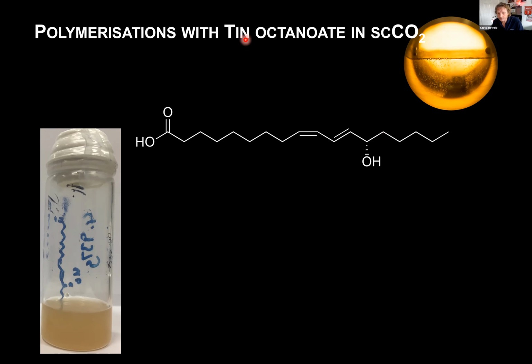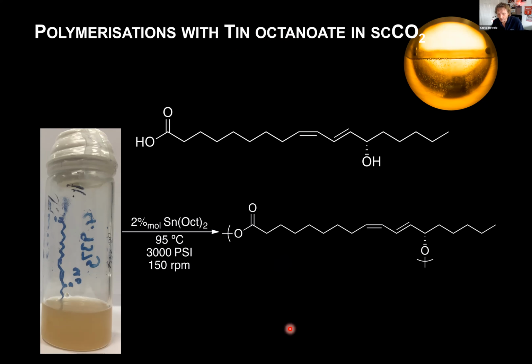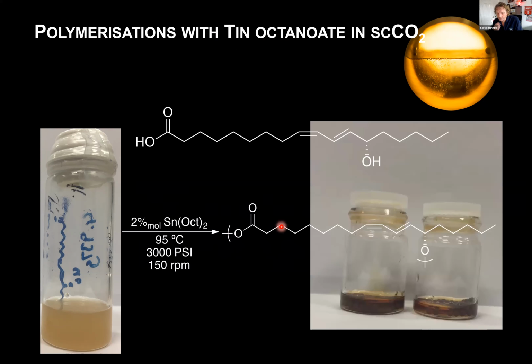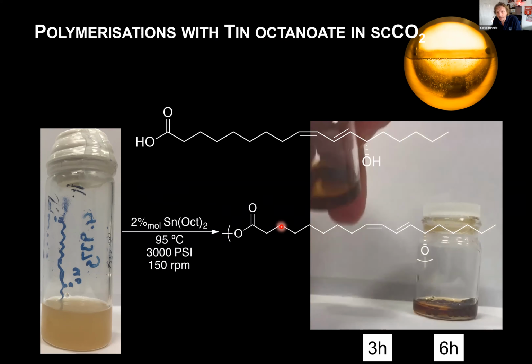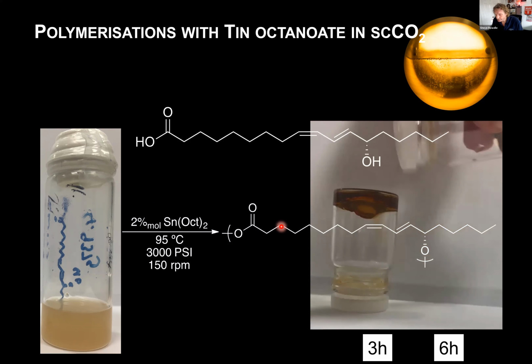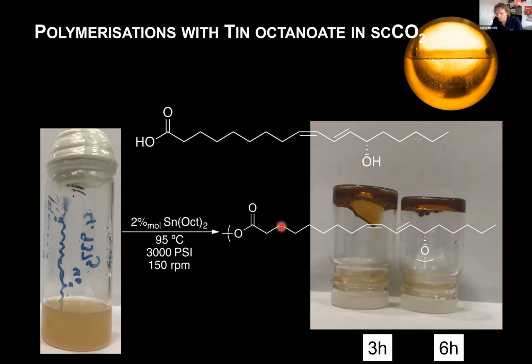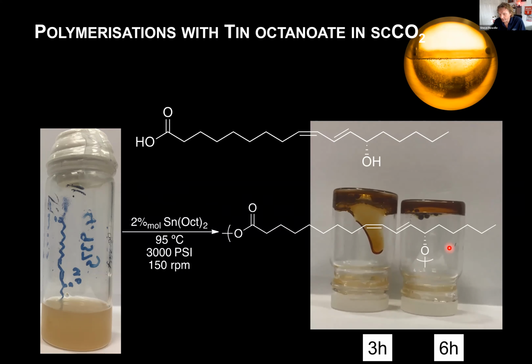We just used very standard tin octanoate, and we did the reaction in CO2, and showed that we could get the polymer to form very easily in CO2. We used quite an elevated temperature to make this happen, but it worked very well. Here you can see an example of the polymers we made. When we ran the reaction for 3 hours, we got a low molecular weight material, which is quite runny. When we did it for 6 hours, we got a much higher molecular weight material, and it showed us that we could get some kind of control.